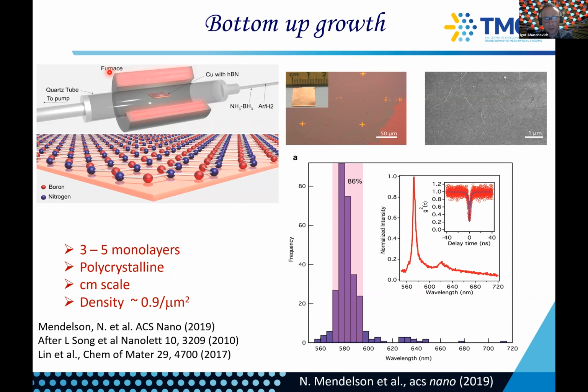And the hBN quality is worse, even worse than on the metallic structure. Of course, that's expected, but you have emitters. The grain size is even smaller. We did some analysis, and it's about 100 to 200 nanometer grains, very small, but it works. Okay. Thank you very much.